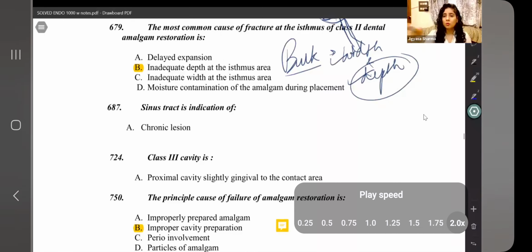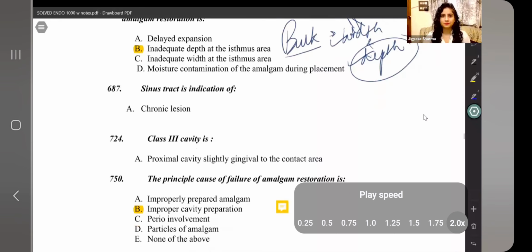Reparative dentine is formed at the dentinal pulp interface in response to that irritation. The most common cause of fracture at the isthmus of class 2 dental amalgam restoration. If you remember, I showed you from Mount and Hume also in the other class that the most likely site of fracture of amalgam is at the isthmus. The cause is insufficient bulk, and the bulk is composed of two things, width and depth. And when comparing the both, the depth is more important. If your depth was inadequate, the chances of fracture would be higher. So more than width, it's the insufficient depth that leads to increased fracturing at the isthmus.